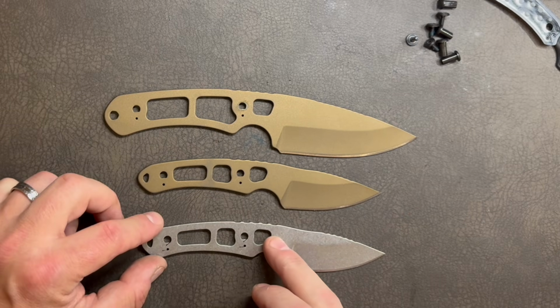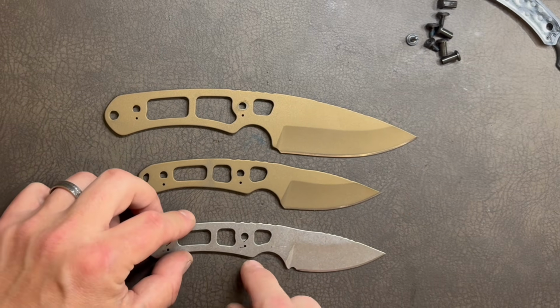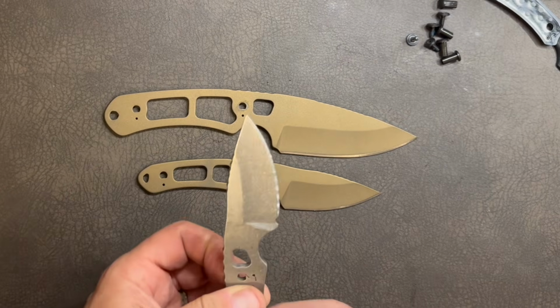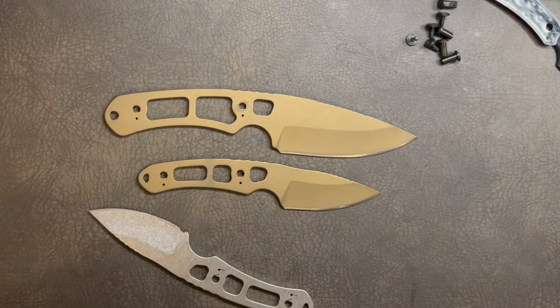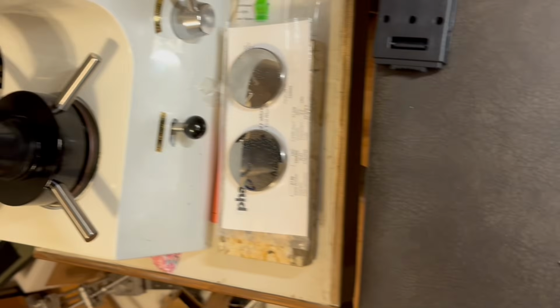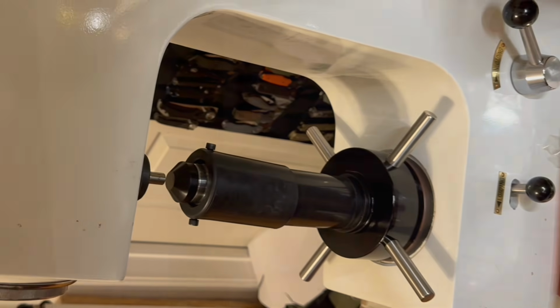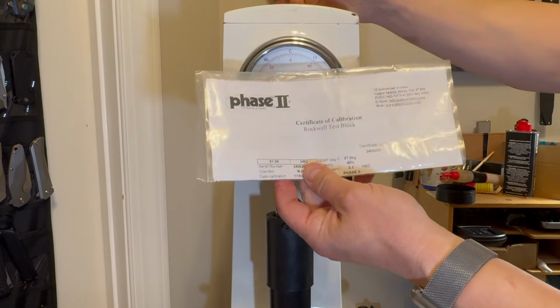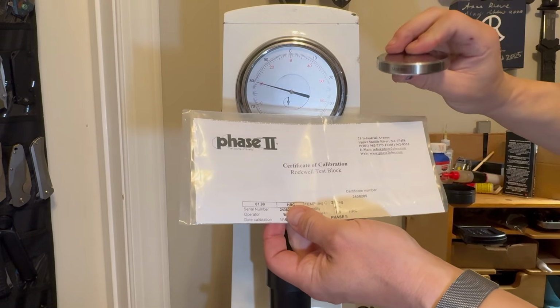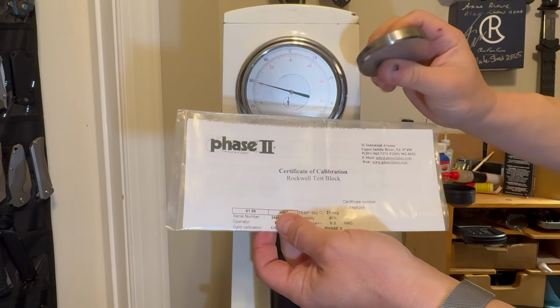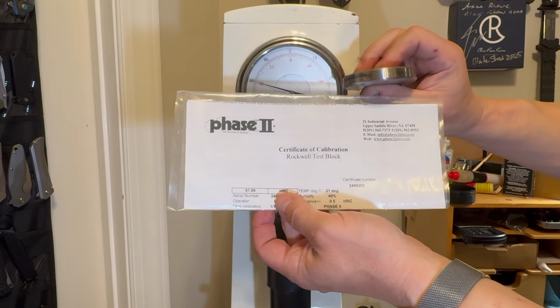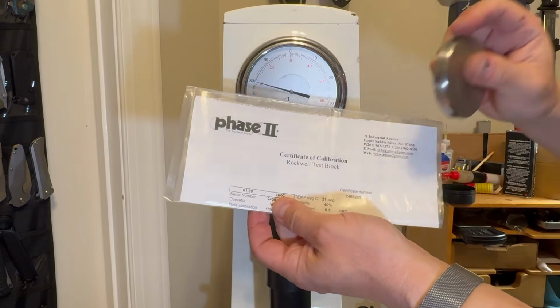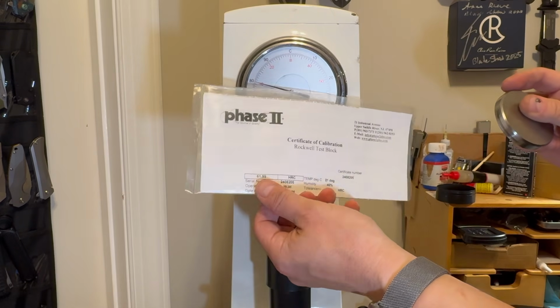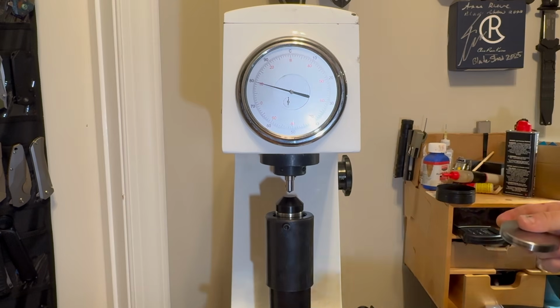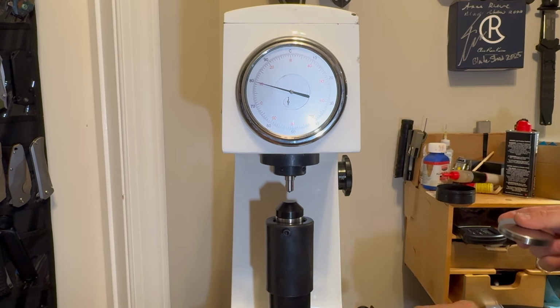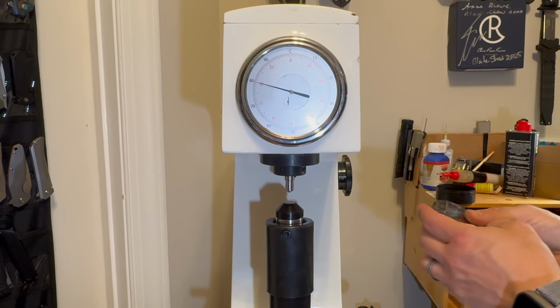Of course, all blades come out of the heat treatment cycles uncoated, and my plan for the day is to determine whether or not Buck planned for Cerakote by increasing the hardness of uncoated blades before they went through that process. As always, before every hardness test, I verify calibration of my Rockwell tester using this independently certified calibration block, which is serialized to this document, and it's rated at 62 HRC. So we're going to put it on the anvil and see how she does.